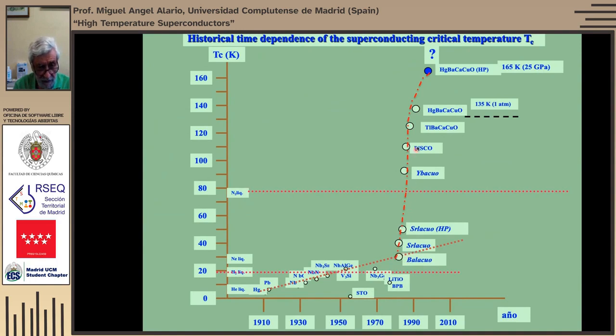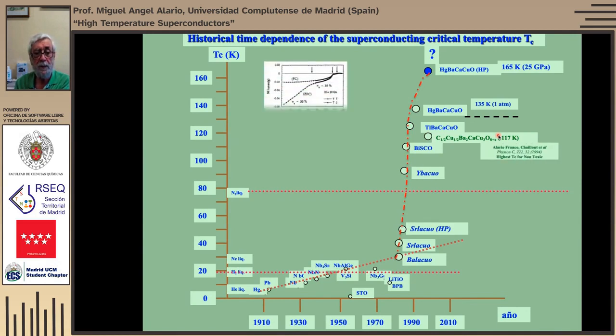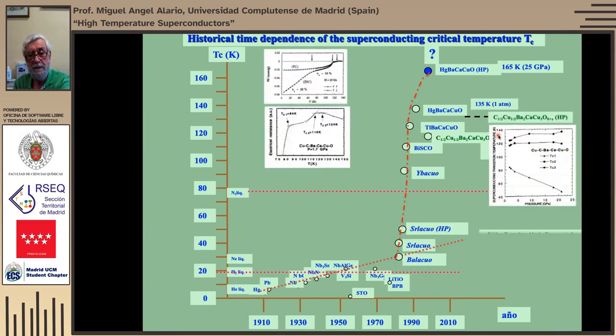All these are enormous things. So it's like the linen for the sails in the boats. Now, we did some work on these replacements, and we got the highest Tc for a non-toxic material, because mercury and thallium and bismuth are all toxic. Well, bismuth not. Also under pressure, we got very high critical temperatures, at 136. But these materials are very difficult to make and not very pure. We made a patent, but it wasn't very useful.